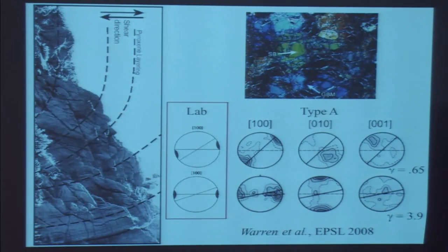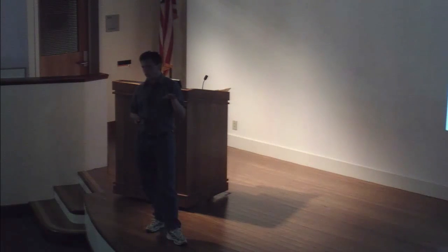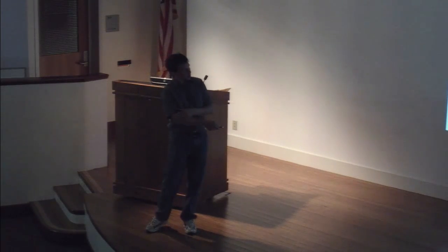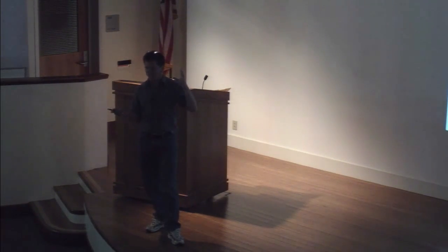So I look at that, and what I see is that explaining the LPO that you observe in the laboratory requires an incredible amount of work. Here in Berkeley, Rudy Wenk has spent much of his career looking at this problem. It's very complicated, and it's still a state of the science issue how exactly this happens. But the fact that the amazing complexity of deformation occurring in the aggregate results in the same evolution of LPO in the Earth and in the lab is a super strong indication that the processes that we're activating are the same in the lab and in the Earth. So it provides a very strong justification for extrapolation of the lab data to lower stresses and lower strain rates.